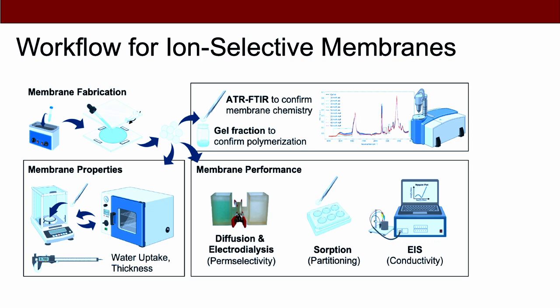So one of my students, Kristen, and this has been in collaboration with Jan Xia's group as well, we are basically designing and trying to do this in a high throughput way, designing membranes that can be photopolymerized. We characterize them, we characterize their properties as well, and then we characterize their performance, which is what we're really interested in. How do we, in a diffusion setup or with electrochemical potential, compare the selectivity of lithium versus nickel, which is the example I'll show you, versus the partitioning versus the conductivity of those membranes.